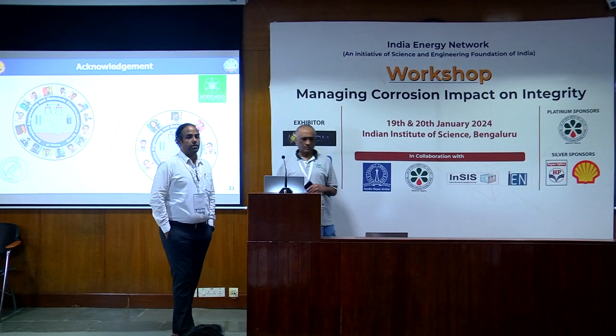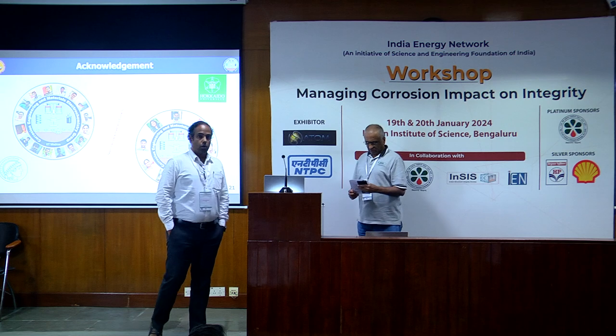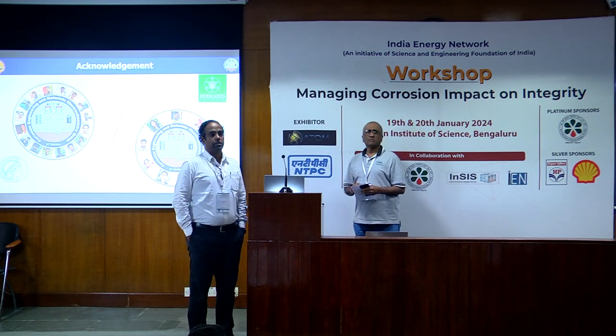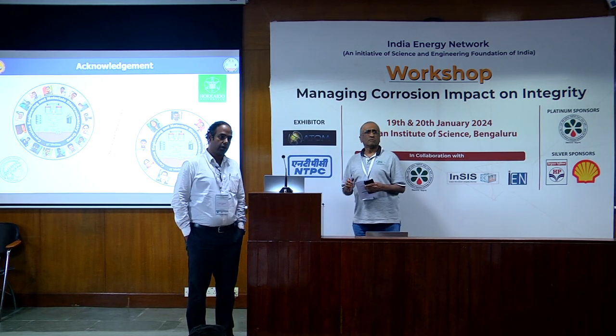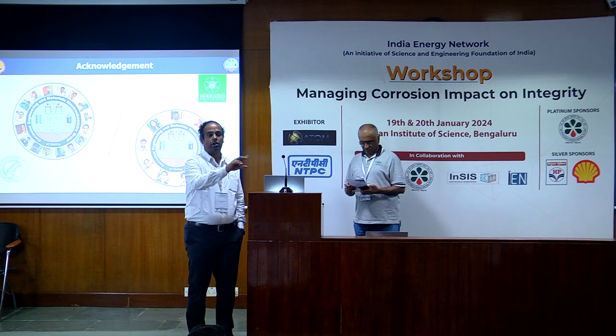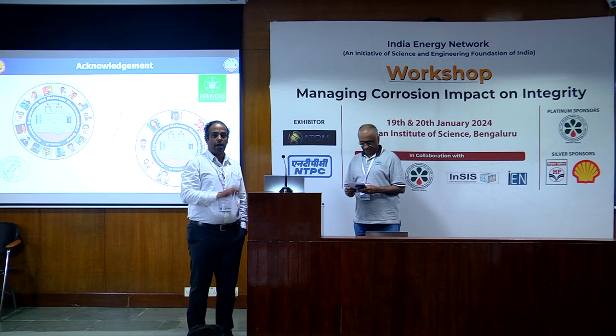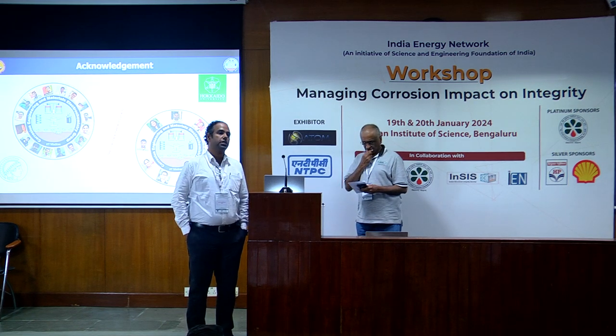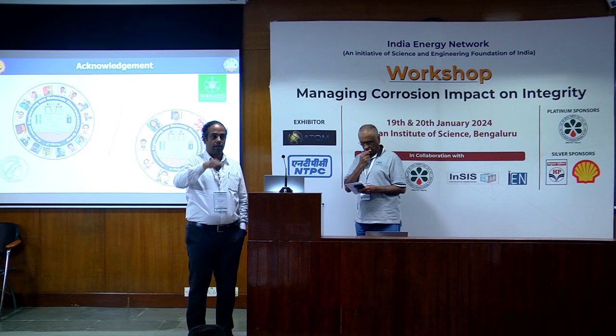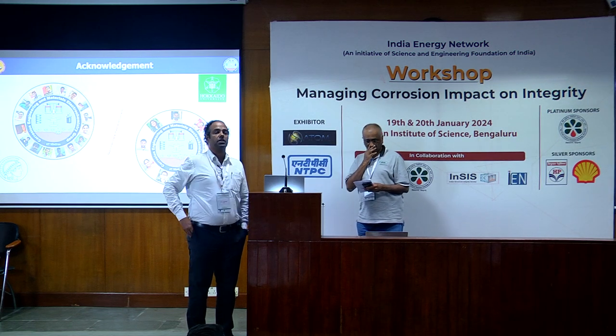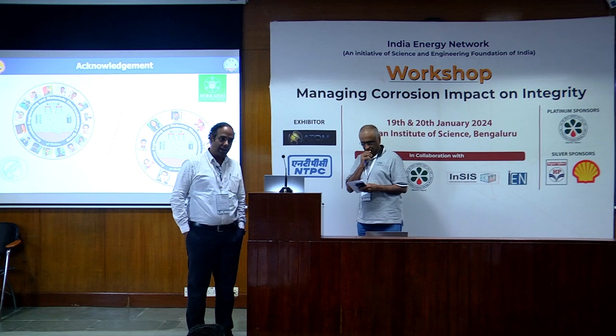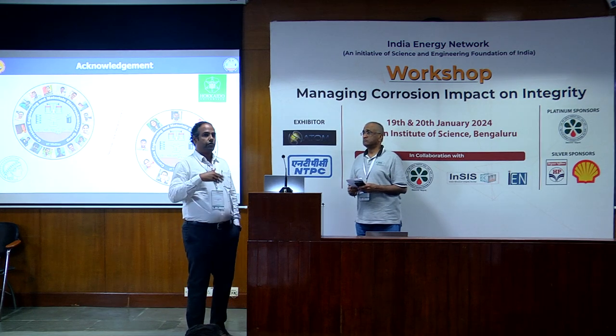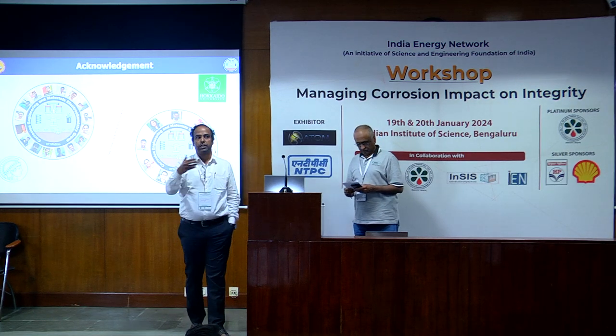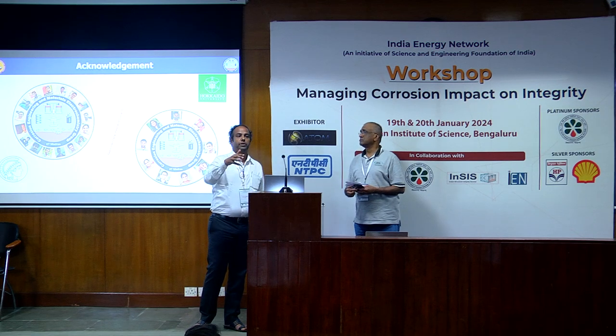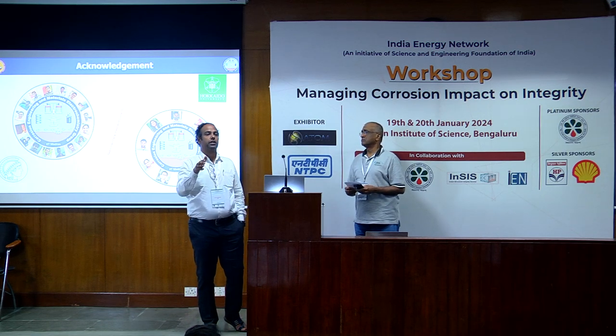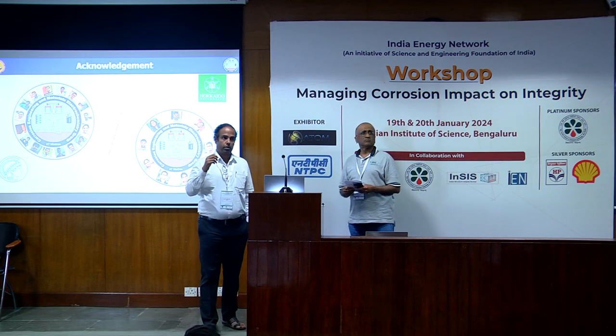Right now, the study is in a very primitive stage. We also do salt spray chamber studies where we look at how the corrosion progresses. Those run-of-the-mill experiments are being carried out on small lab scale specimens, not on larger scale coupons. We also look at the local scratch parts. What are the precipitates, or what is the corrosion product therein? That is how we say, if I compare, let's say, for 168 hours of test, I see that the presence of these particles actually retards the zinc dissolution component.